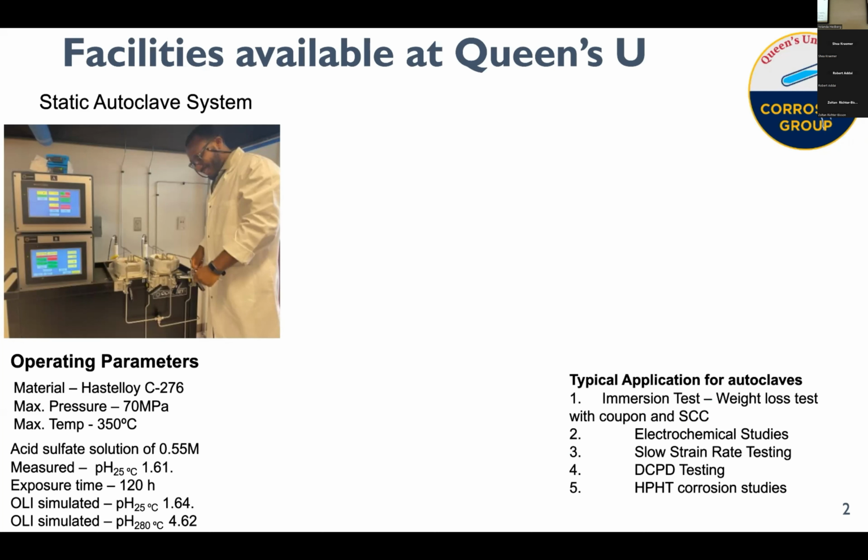In a steam generator, there tends to be what they call heat transfer crevices, which occur between the steam generator tube support plate and the steam generator tube. At that little crevice there tends to be a large deposit of impurities. So in our lab, we're studying the behavior of those impurities. Someone else is working on chloride, another person on lead caustic, and I'm working on acid sulfate.